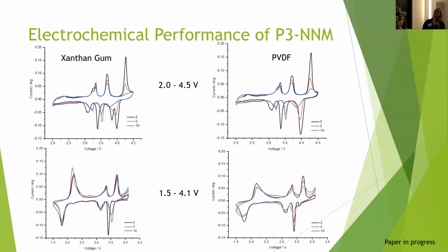So at high voltages, you can see these redox peaks really quickly go down in intensity, and that's probably the main cause of my capacity fade. So I need to figure out what that is due to. I've read that it could be oxygen redox, so I could get oxygen gas coming off my material and hence loss of active material. And that's why I see a rapid decline in capacity, but I need to get that confirmed.